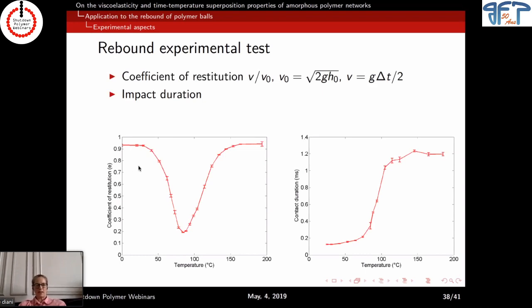So we look at the coefficient of restitution, which is basically the height of the rebound divided by the drop height. And if you have an elastic material, you should get 1. Well, we know in polymers there's no perfect elasticity, but unfortunately, we didn't verify with a metal bead that this is not due to the experimental setup, and that we would really get 1 for an elastic material. But what's interesting is that you can see how with the temperature, the rebound is dramatically dropping.